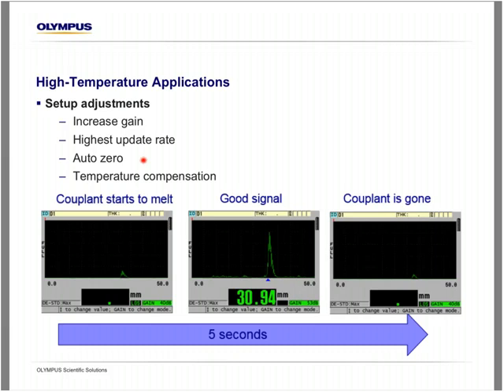You can use the freeze key on the 38, which holds the reading on screen. So you can limit how long you have that transducer on the hot pipe. You can couple on. As soon as you get that signal over 20%, you can hit the freeze key, uncouple, and then from the frozen waveform, you can actually make internal adjustments to either the gain or blanking settings. And then also, you want to use temperature compensation. So that's a unique feature on the 38 that we'll discuss.